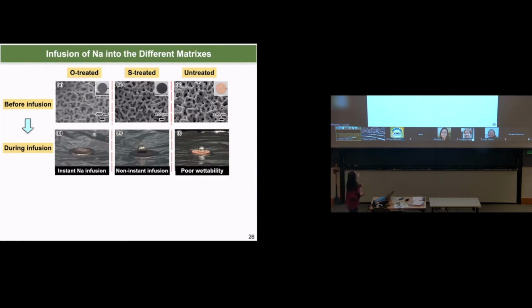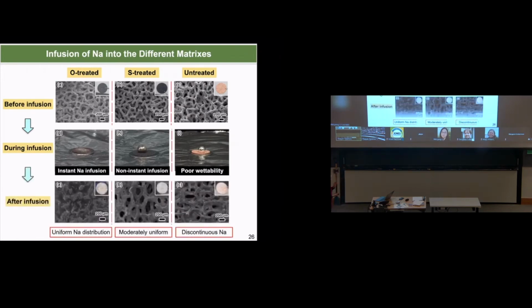However, if we compare to the untreated one, the sodium doesn't really wet the copper foam surface. You can see the sodium droplet right here shows a very poor wettability. The sulfur-treated one is kind of in the middle between the oxygen-treated and the untreated one. The reason could be that the flaky-like structure gives a poor wetting angle. That might be one of the reasons that sulfur doesn't work as well as the oxygen-treated case. So we got a uniform sodium distribution, especially for the oxygen-treated case. For the non-treated case, we have a discontinuous sodium infusion here.